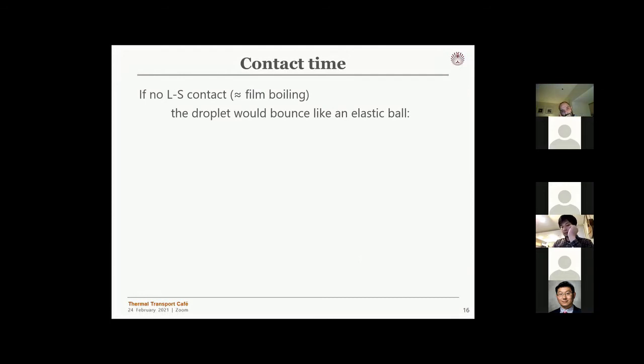We've also done some calculations based on the elastic model of droplet bouncing, which can be used as a reference. This is the droplet contact time as predicted by the elastic bouncing model, which assumes there's no liquid-solid contact—corresponding to the film boiling regime. So in film boiling regime, we should have a contact time around this value.